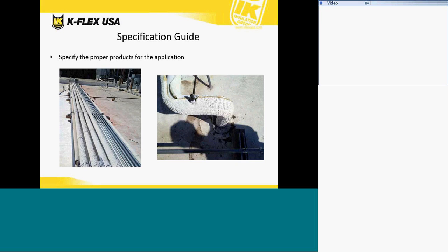You want to make sure that you specify the proper products for the application. As you can see here, this is a white insulation specified for an outdoor application. I'll start with that all outdoor applications should have, at a minimum, a UV protective coating on the insulation, and even better, a protective jacketing. But if neither are specified, then none will probably be applied. The black insulation, when installed outdoors, has carbon black in the mix, and carbon black acts as a UV stabilizer, which will prevent UV degradation for a little bit of time. As you can see here, though, the white insulation does not include carbon black in the production process. This degradation happened over the course of about 4 months. So be aware, and this is a way to hit home, that you need to specify the proper products for your application.